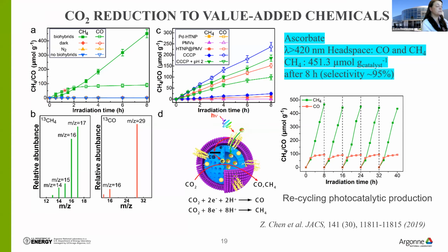So within the first 2 hours, only CO formation was observed. And then it came to plateau. However, after 2 hours, the key product was methane. And again, there is no reaction in dark. There is no reaction in atmosphere of nitrogen. And also, it's very interesting, if we started from CO, not CO2, we also did not observe any methane formation.